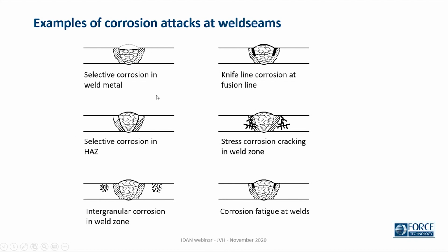To get a little overview of different problems with welds, we could have that the weld metal itself is not as resistant as the base material, causing selective corrosion of the weld metal. We could have selective corrosion in the heat affected zone. That would be a risk if we have a very noble weld metal and no protection of the material. Then the part closest to it would be sensitive, or it could be the precipitates or grain structure in the heat affected zone, which cause it to be more sensitive to corrosion.